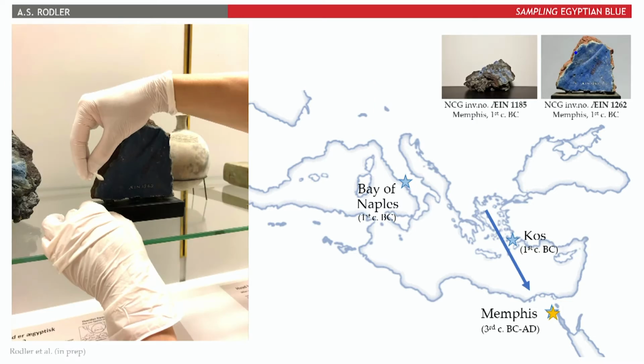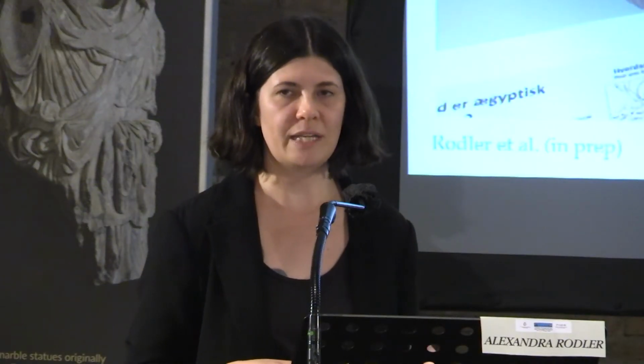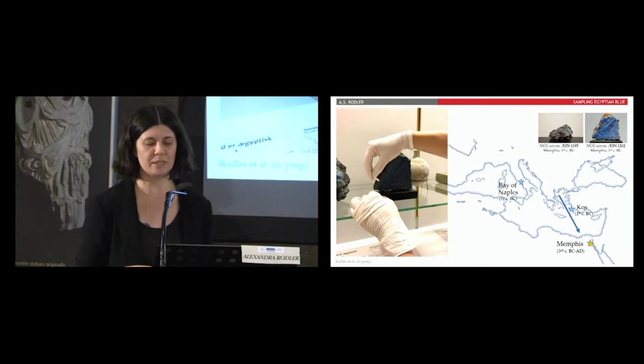Okay, so to add to refining sample strategy with several samples per paint layer, we also recently tested a new sampling method here. It used a cotton swab suffused with low concentrated nitric acid to collect Egyptian blue from this artifact from Memphis that you already saw before. So I sampled previously already analyzed samples, and I collected in time intervals of 10, 30, and 90 seconds, and also in duplicates, of course, to compare to the previous results and also to see how reliable these results are.